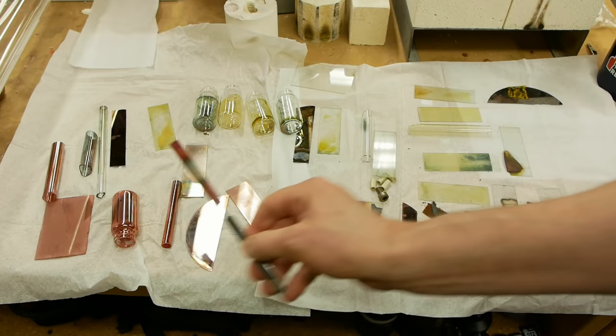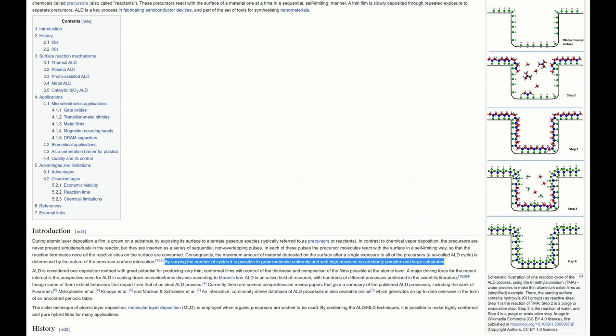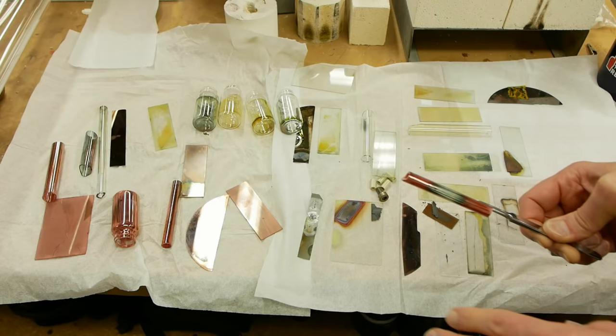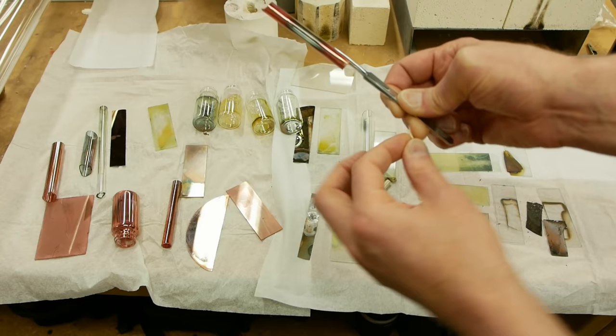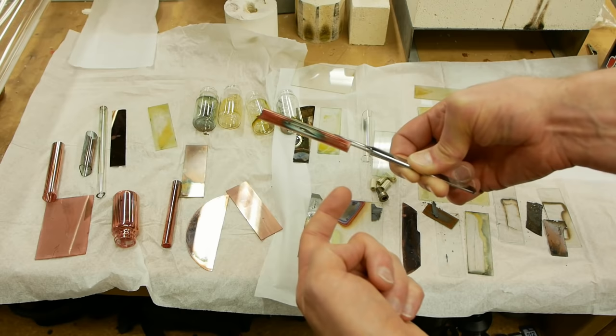However, check this out. I just told you that this technique is amazing because it builds up a very uniform layer, atom by atom. And if you search for atomic layer deposition on Wikipedia, it'll say we lay down a layer of atoms and then another one, so it's perfectly uniform. And one of the things that ALD is used for is coating very deep holes. So imagine you had a hole that was one millimeter in diameter and a meter deep. ALD is actually able to coat the inside of that hole completely uniformly with a metal or ceramic.